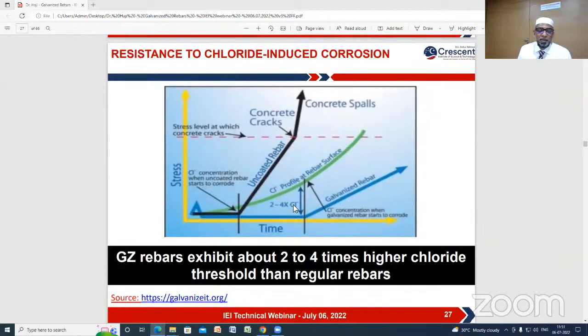This slide is very, very important. This slide shows the time versus stress in the building, and the green color curve shows the chloride profile at the rebar surface. You can clearly see that at a lower chloride level, if you use uncoated rebar, the distress starts, the corrosion is initiated, and beyond some level, cracking and spalling happen.